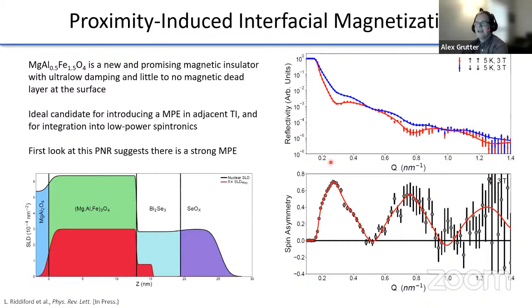So the reason that magnesium aluminum ferrite was chosen is that it's a very promising magnetic insulator material, actually mostly used for ultra low damping applications. But what's nice is it has little to no dead layers at the surface, so it should have really nice contact of the magnetic layers. It also is very, very insulating, so transport measurements should really primarily probe the bismuth selenide. And it tends to be relatively sharp and high quality when you grow it. So it's a really ideal candidate for inducing a magnetic proximity effect in an adjacent topological insulator.